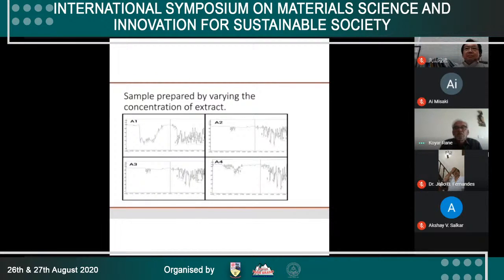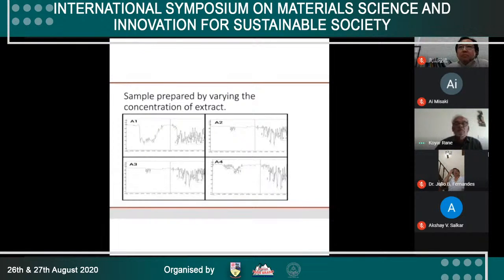Sample A2 is prepared using 2 ml extract. Here, the band representing the presence of aromatic compounds changed to a shorter wavelength region, that is 2920.23 cm⁻¹. The band at 840.96 cm⁻¹ represents the NH bond, which has also moved to a shorter wavelength region. The spectrum of sample A3 is similar to A2. Finally, sample A4, which contains 4 ml extract, shows a peak at 3344.87 cm⁻¹, which represents OH stretching.